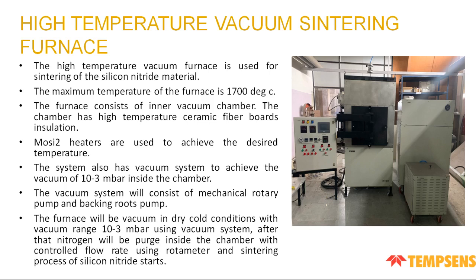The furnace consists of an inner vacuum chamber. The chamber has high temperature ceramic fiber board insulation, and molybdenum disilicide heating elements are used to achieve the desired temperature. The vacuum system consists of a mechanical rotary pump with a roots pump. The furnace is vacuumed in dry cold condition with a vacuum range of 10 to the minus 3 millibar using the vacuum system. After that, nitrogen is purged inside the chamber with controlled flow rate using a rotameter, and the sintering procedure of silicon nitride starts.